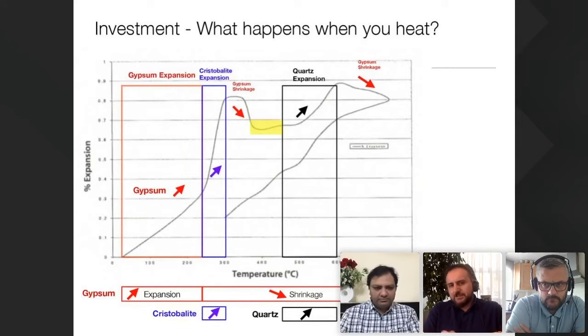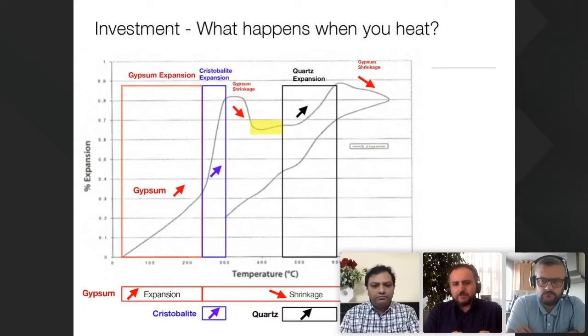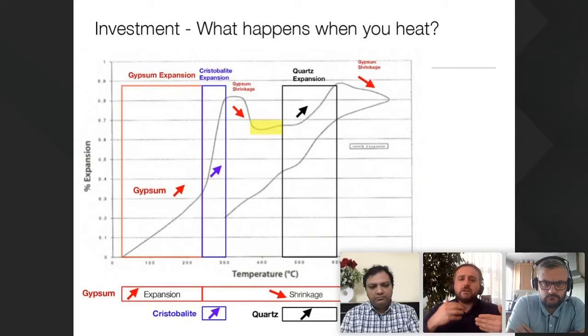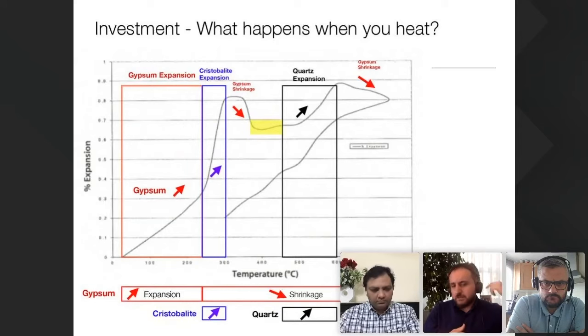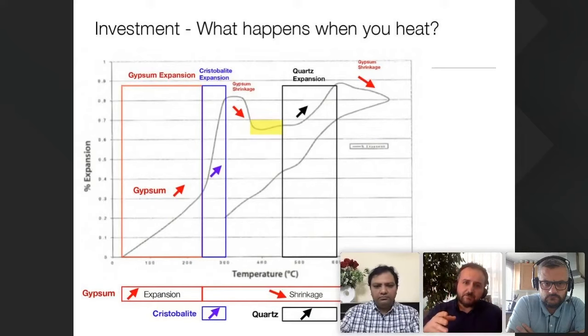After that you have a high expansion side, around 250 up to 300 degrees, where the cristobalite element is also expanding. So the gypsum was expanding, but now there's a very huge force of expansion due to the cristobalite component inside the gypsum, which after a while actually makes the gypsum shrink - it's a reverse effect. And because the cristobalite expansion has ended, you see that expansion going down.